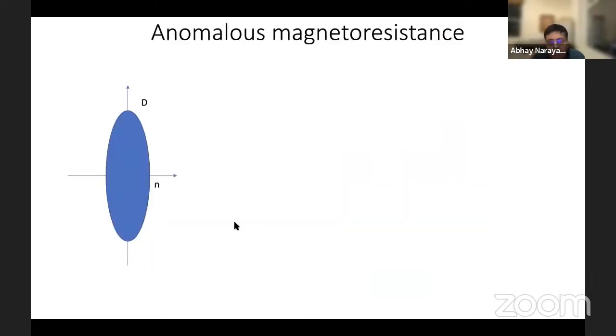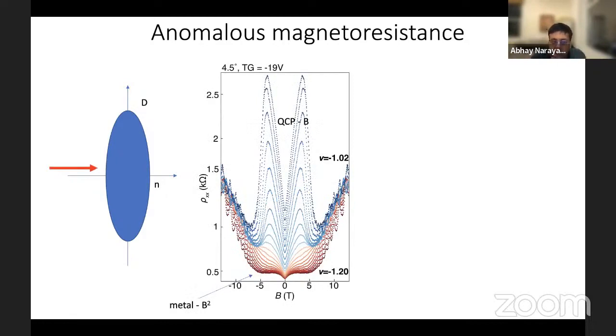Okay, so finally, before I conclude, in many correlated materials, also anomalous magnetoresistance has been observed at low field. And in our materials as well, we see this anomalous magnetoresistance behavior. So if I measure the resistance as a function of magnetic field, here are shown a set of traces. This red curve here is taken far from the quantum critical point, and the top blue curve is approaching the quantum critical point. If you're far from the quantum critical point, perhaps not very obvious here, but you can take my word for it that the B dependence is B squared, as one expects for a simple metal.